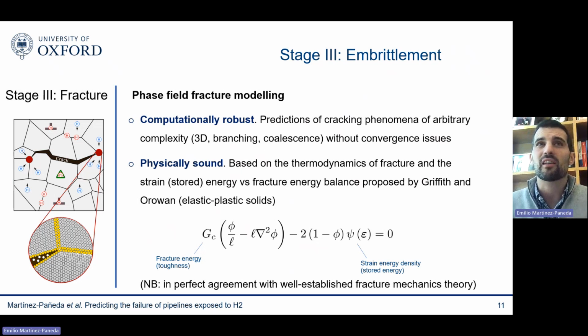But the other critical aspect is that it's physically sound because it's based on the thermodynamics of fracture, basically a competition between the strain energy and the fracture energy. This is a balance that was first proposed by Griffith and then extended by Orowan to elastoplastic solids. And basically you see the governing equation here. So it's a competition between the strain energy density, the stored energy in the material that increases with mechanical straining. And whenever the energy stored in your material is large enough that it can create two new surfaces, then you overcome this fracture energy and you see cracks growing.